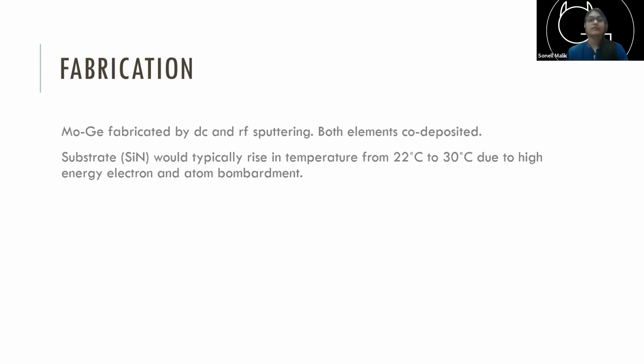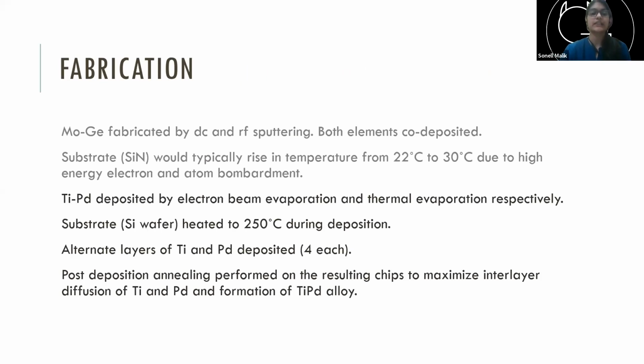So how I fabricated them. For molybdenum and germanium, I used DC and RF sputtering that I told you about earlier, and they were co-deposited. I deposited them at the same time. And the substrate I used was silicon nitride. For titanium and palladium, I used electron beam evaporation to deposit titanium, and for palladium, I used thermal evaporation. And in this case, I couldn't co-deposit them. I couldn't deposit them at the same time.